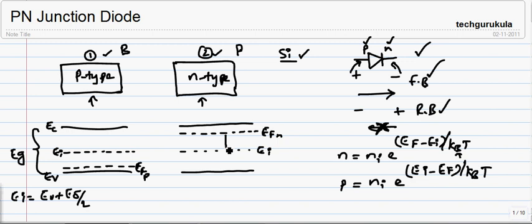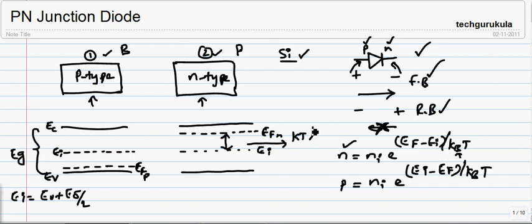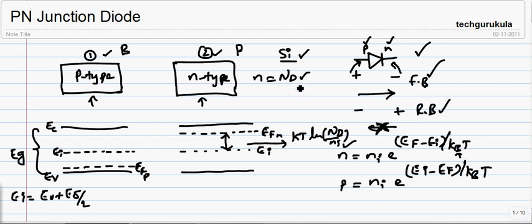This difference EFN minus EI — if you use the equation for N and solve this — you will get an equation like KT times ln of Nd by NI. The reason we write this is that in N-type material, the number of electrons is approximately equal to Nd, where Nd is the doping concentration, that is the number of dopant atoms per centimeter cube. And the number of holes will be approximately equal to NI squared by Nd.